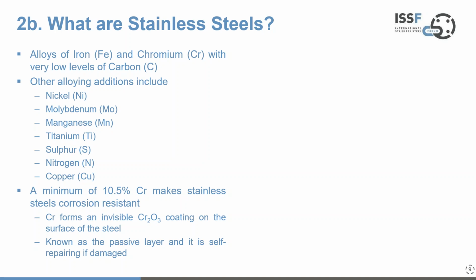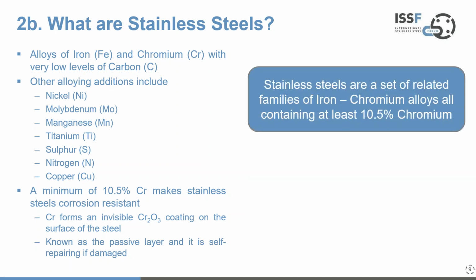Well, fundamentally, stainless steels are alloys of iron and chromium with generally very low levels of carbon. And I've listed below a few of the other alloying additions. That's not an exhaustive list, that's just some of the popular and critical ones. But I think it's very easy to say that stainless steels are really a set of related families of iron chromium alloys, all containing at least 10.5% chromium. And that's a critical content because it's that level of chromium as a minimum that makes stainless steels corrosion resistant.